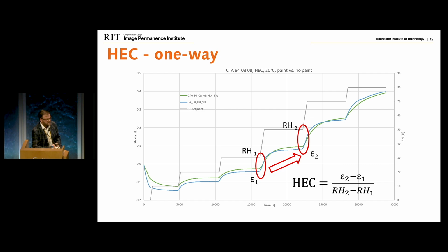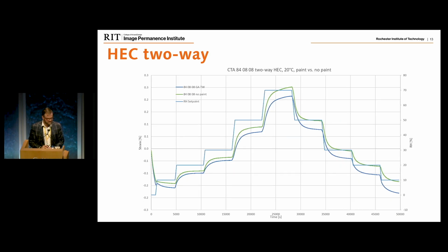Now, how the HEC is calculated is very simple. You take the difference in RH at any given point. We're using the steps that we have chosen. And you take the difference in strain, divide one through another. And what you're getting essentially is a strain cost of increasing your RH by 1 percentage point. And this is how the curve looks for the two-way test. There we go. Again, these are two curves of the same polymer, one with paint, one without it. I'll go into those details in a second.